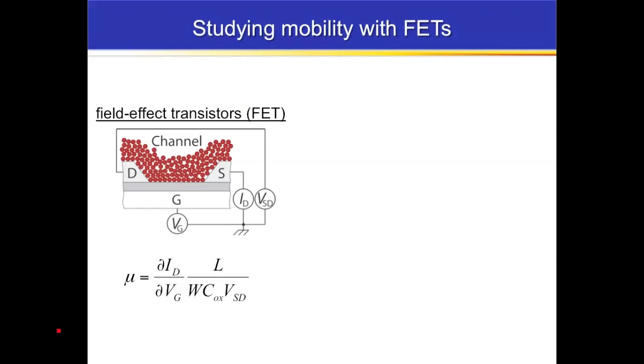So we spend a lot of time trying to understand charge transport in these materials in order to try to improve the diffusion length of the minority carriers. To do this, we're often using a platform that's called a field effect transistor to determine mobility. A field effect transistor is a 3-terminal device, and basically what we're doing is we're modulating the current that flows between a source and a drain by using a gate field. And by changing the gate field, we can calculate what the mobility is. It's going to be proportional to the slope of the drain current divided by the voltage on this gate field.